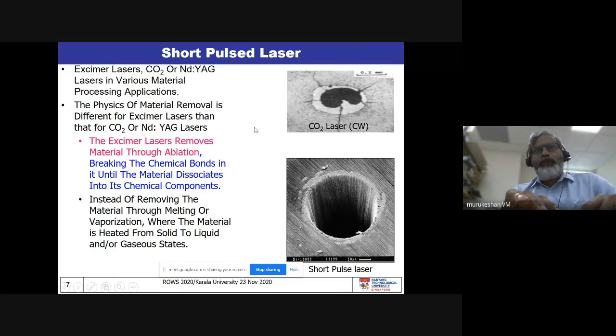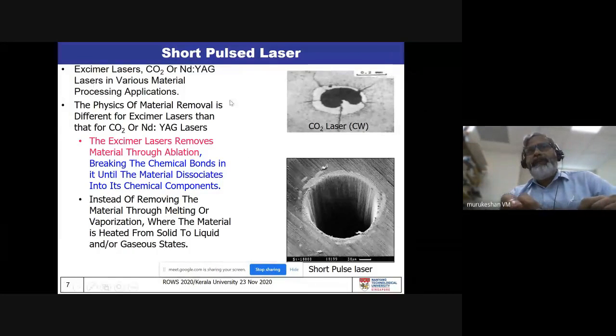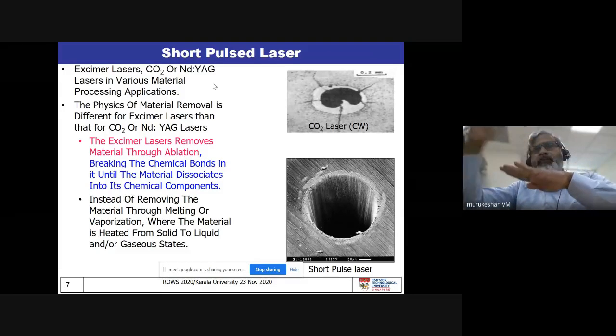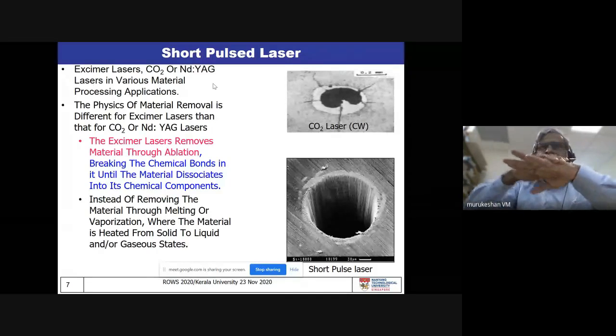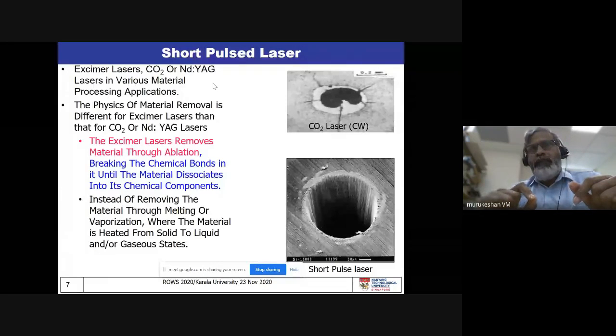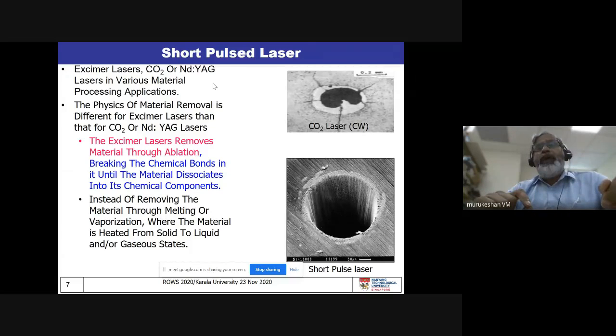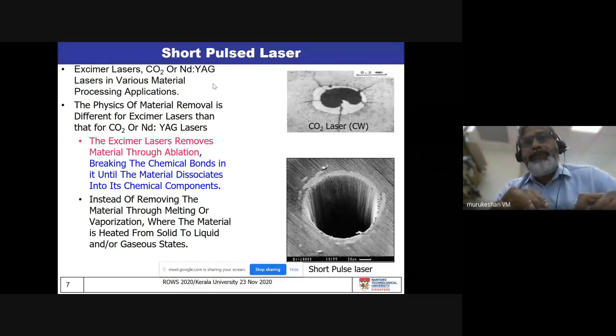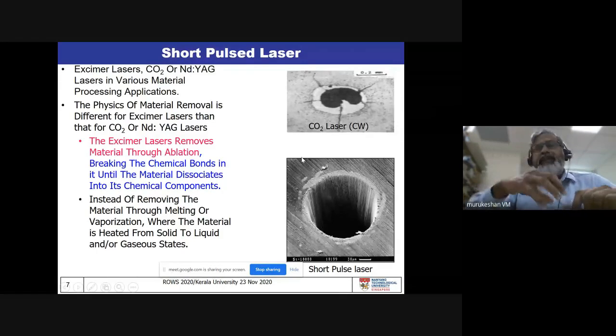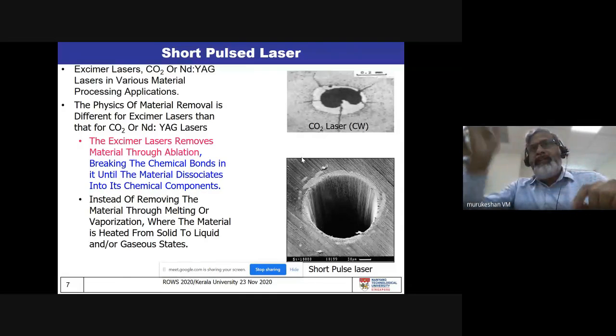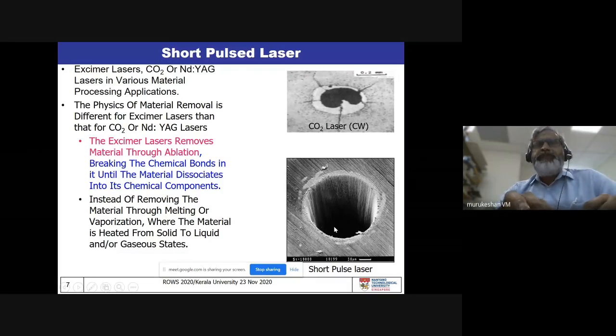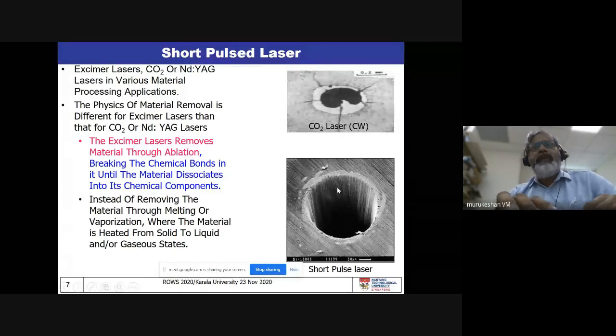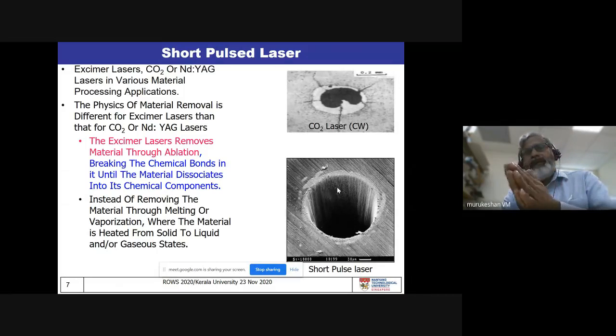But if you compare this against the short pulse lasers, such as excimer lasers, the material removal process is slightly different. In the case of continuous wave lasers such as CO2 and Nd:YAG, the material removal is from solid state to liquid state to vapor phase. There's a real phase change of material from one phase to the other. In the case of excimer lasers or femtosecond lasers, the pulse has enough peak fluence that it is going to break the chemical bonds by the process called ablation. So breaking these chemical bonds directly will take the material from the solid state to the vapor phase. In such cases, you can see the processed region has very subdued side effects such as heat affected zone. So it is much more preferred in very many feature fabrications, whether in the macro scale, micro scale or nanoscale, depending on the applications. So these are some of the fundamentals I would like to highlight here.